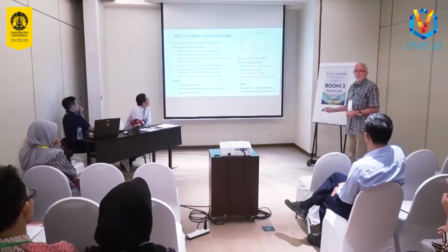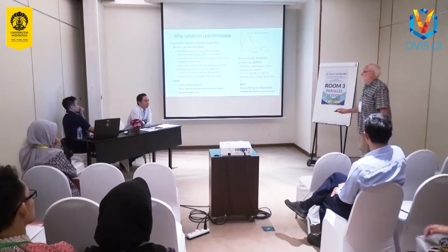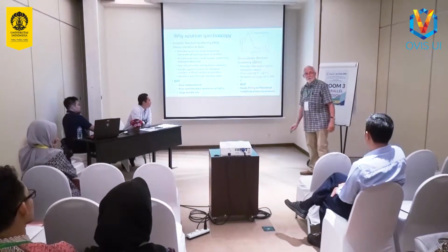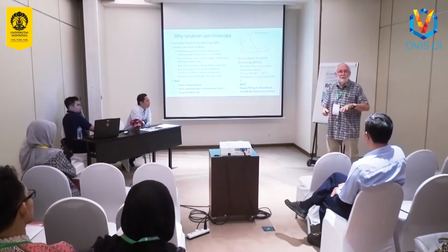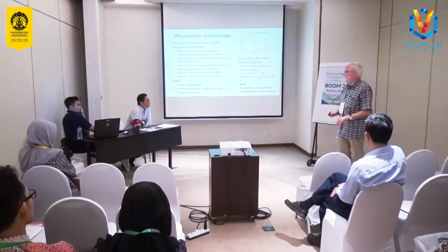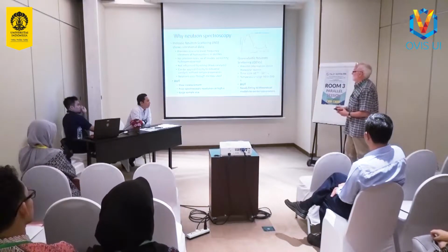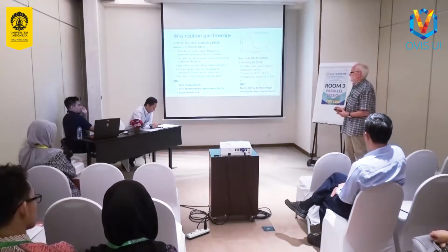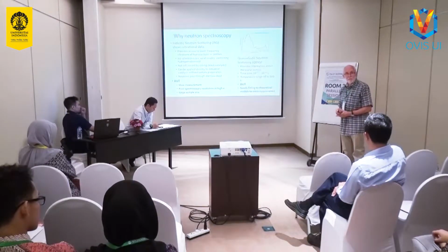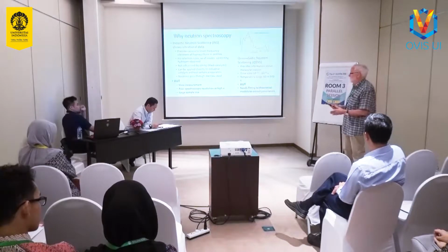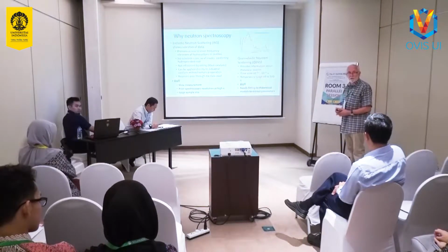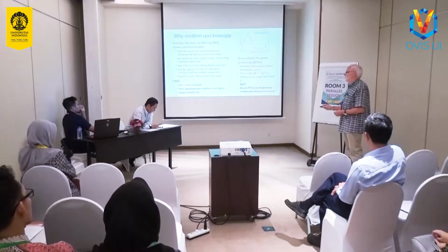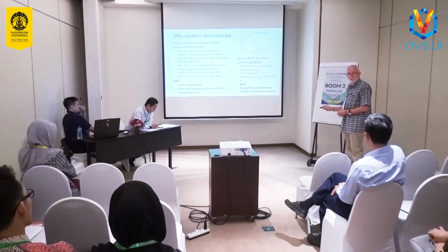So there's a number of practical advantages here to using neutrons for getting vibrational spectrum. But of course, as always, there are some drawbacks as well. One of the drawbacks is that it takes a long time to collect a spectrum because neutron fluxes are not very high, the number of neutrons involved is small, and typically for a catalyst sample containing a small amount of adsorbed molecules, it may take us 6 or 8 hours to collect one spectrum. Whereas infrared spectroscopy these days we do in less than a second. So the measurement is slow. We can't do in situ studies of reactions because we can't measure the spectrum fast enough.